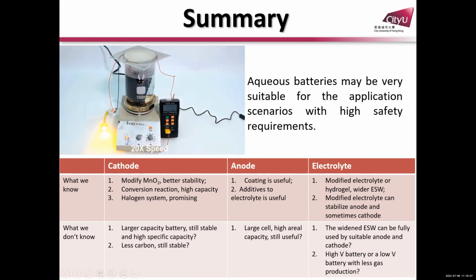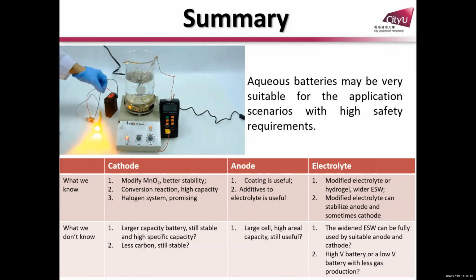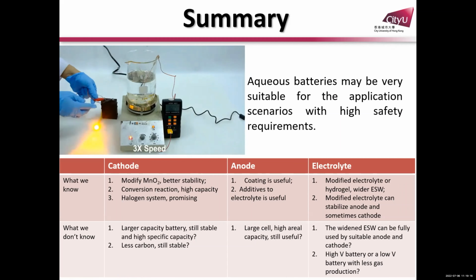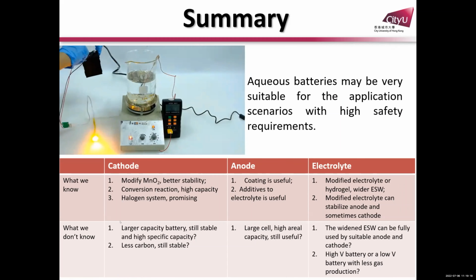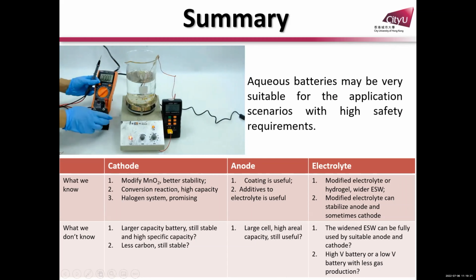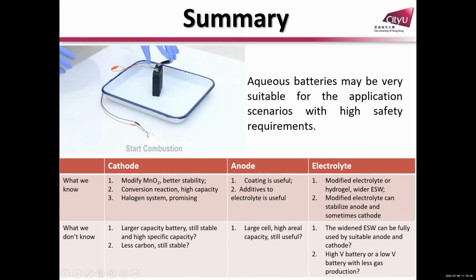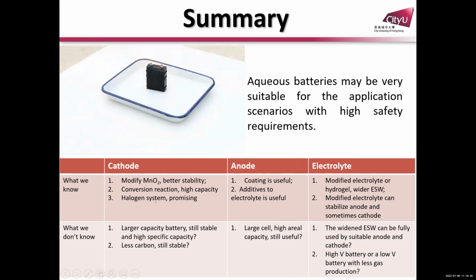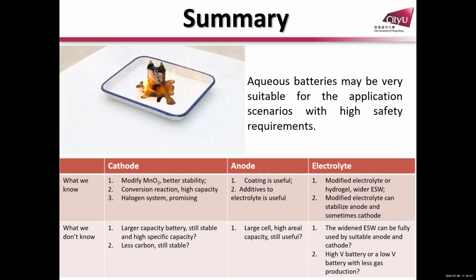For the cathode side, manganese oxide, we basically think manganese oxide generally follows a deposition mechanism. If you fabricate a small battery, it's good. If you fabricate large size batteries, it becomes a big issue. And conversion reactions provide very high capacity, but some materials are quite expensive. The halogen system is permissible only if you can immobilize the halogen materials in some structures.